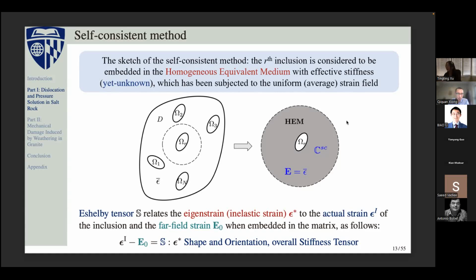The eigenstrain is defined as all types of inelastic strain in this inclusion. It can be considered as the plastic strain, viscous strain, or the thermal misfit strain, all these types of inelastic strain. And in this linear relationship, we have a very important tensor we call the Eshelby tensor, which is S here. It is a fourth-order tensor that provides us with a linear relationship between the deviation of the strain and the eigenstrain or inelastic strain inside the inclusion. So that is the fundamental equation.